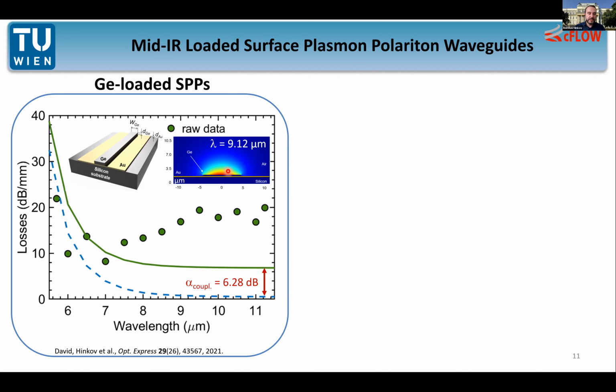A nice feature of this is that still a significant portion of the mode is guided outside, so we can use this for sensing. And germanium is well known to be very broadband in the mid-infrared, and therefore it can really cover a wide wavelength range from 5.6 to 11.2 micron. In this case, we could nicely show that we have relatively low losses for such a waveguide geometry.